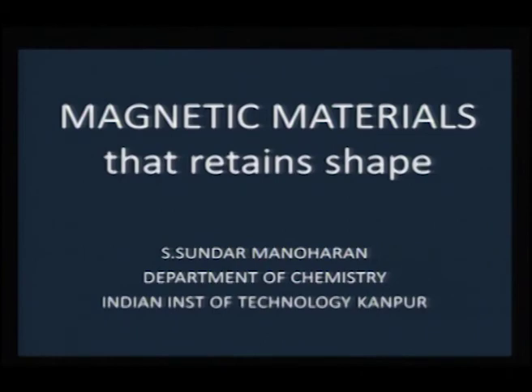For example, in the case of manganites, we said the magnetic property of manganites controls the electrical conductivity, and the two properties go hand in hand, which we call the dual property of magnetoresistance, where magnetism governs the resistivity of that material. And we have also seen how this effect is pronounced in multilayers, and we were talking about tunneling magnetoresistance. Also, as another example, we showed how we can transform an insulating or a semiconducting material by carefully doping some magnetic impurity; even with a low level of doping, say 1 or 2%, you can still transform that material to go magnetic.